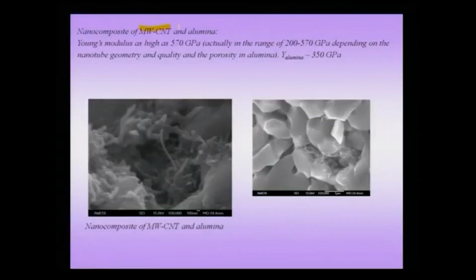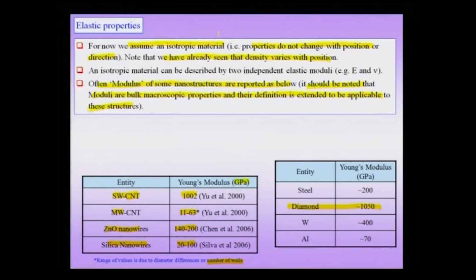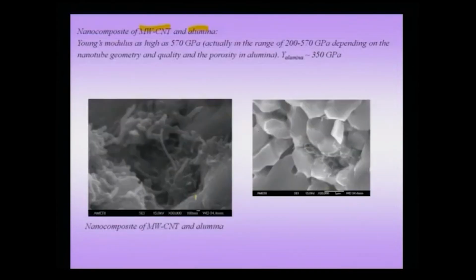Therefore, if I am making a composite, the modulus benefit I get has to be between these two limits. The composites we will be referring to very soon are the nanocomposites, wherein we will be using a reinforcement which is in the nanoscale. One such example is the multi-walled carbon nanotube reinforcement of alumina. Of course, as we have seen, it is better to reinforce the system with single walled carbon nanotubes, but it is easier in many cases to manufacture multi-walled carbon nanotubes and reinforce with those. You can see that the grain size itself is of the order of microns. So, this is not a nano grain size alumina, but a micron grain size alumina, and what is nano in this whole nanocomposite is these carbon nanotubes which you see here in high magnification.